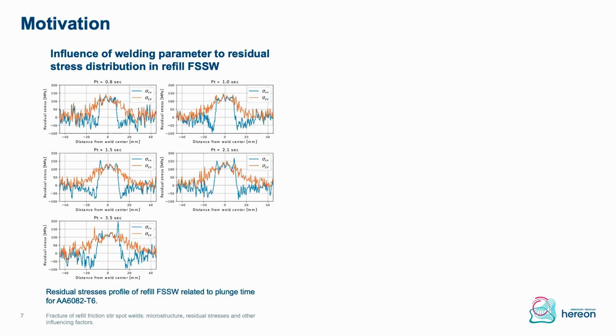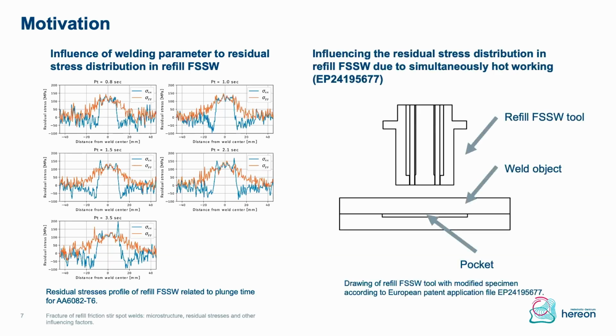So we came with a different approach, which you see here on the right-hand side, where we influence the residual stress profile due to simultaneous hot working. That was done where we milled a pocket basically in the lower sheet, and due to the applied clamping force, the upper sheet gets deformed into the lower sheet.